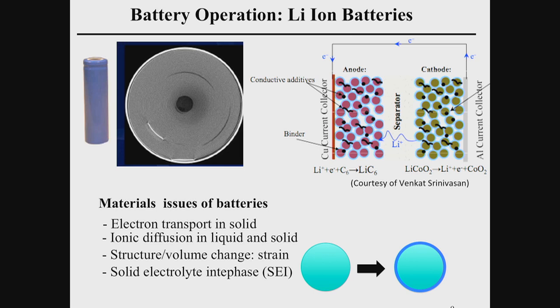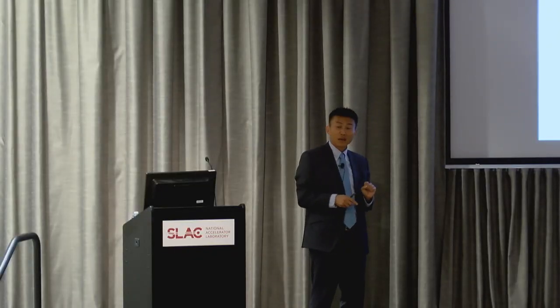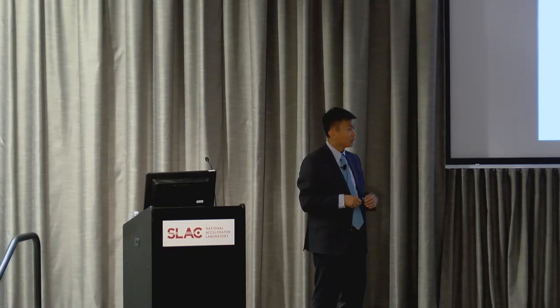So that allows you to have this battery running for multiple years. So you need these few things. Now let's come back to this basic structure and see how we get high energy out of it. You increase the voltage. The voltage is defined by these materials. There's actually a limit, because the higher the voltage, the more you decompose your electrolyte. We are now already reaching somewhere close to 4.5 volts. The most we can probably do is 5. So we have only about 10% to go higher.